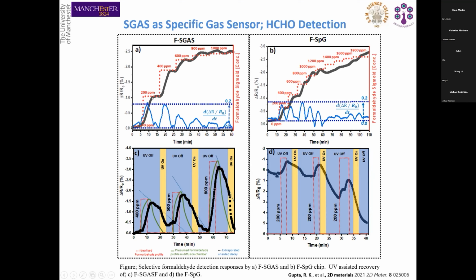But what is most important with the graphene-based gas sensor is the recovery of the sensors. If you look at existing technology like metal oxide semiconductor, to recover the sensor from whatever deposition of material goes on it, we have to heat it at a high temperature. At the same time, we need to pass a high current. But with the graphene-based technology that we use, we could only use a small, low power UV irradiation. This low power UV irradiation will easily make your sensor recover.